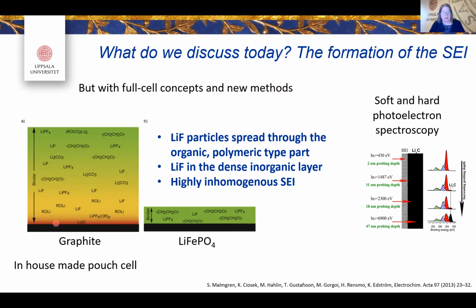So in this case, we cycle the graphite versus the lithium iron phosphate. And just to make a long story short, you have the much thicker SEI. You have the inorganic species close to the graphite surface. You have lithium fluoride all through the layer. You have more of the organic type materials here. In this case, depending on the binder you have, you can even have almost like a jelly type of electrolyte all the way also in this.